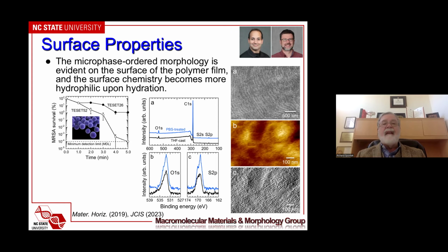And lastly, just to put things in perspective, this is what we find. This is now the survival of MRSA, which is a highly drug-resistant bacteria. And if we have 52 mole% of this polystyrene mid-block sulfonated, we can get down to minimum detection, which is a 6 log unit reduction. So we're talking 99.9999% inactivation within 5 minutes of exposure.